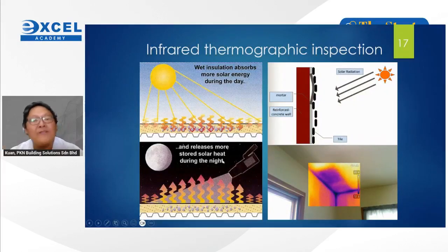And diagrammatically, I would like to explain. Okay, let's say for the first diagram on the upper left, under the hot sun, an area with waterproofing failure has one layer of water pocket under the surface. Under the hot sun, it absorbs more solar energy than the dry concrete. So wet concrete and dry concrete receive the same energy. But in the evening, the water pocket will remain hotter, and we are required to look for hot spots and verify with a moisture meter that can penetrate 20 mm from the surface. And for the inspection of facade, because the water is very close to the surface, it becomes hotter once it's exposed to the sun. So for facade, we also look for hot spots.